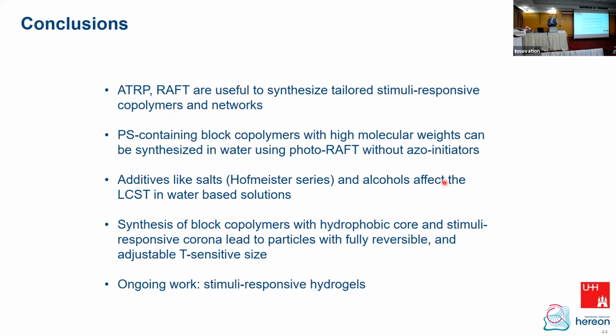I hope I could convince you that with controlled radical polymerizations, we can really play with many different sorts of monomers, also interesting monomers, stimuli-responsive systems. We can go all the way to homopolymers, block copolymers, but also networks, if we finally cross-link these systems in a controlled way. We have access to high molecular weight polystyrene. I did not stress that point too much, but we can make polystyrenes with molecular weights up to 300 kilogram per mole with reasonable control using this sort of PISA process.